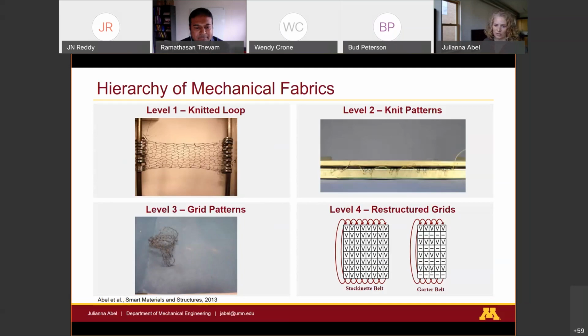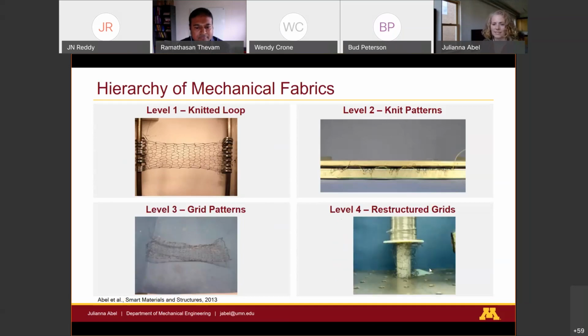And then we can create structures. We can enhance our forces or displacements by going from a 2D element into a 3D structure. And so this is a tube that acts as a deployable boom to produce 400% actuation strain under more than 5 times its weight. And so we have a lot of potential at each of these levels to tune behavior for different applications.